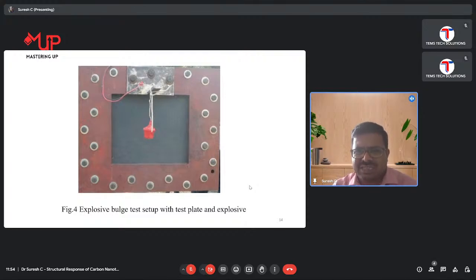The fixture is 550 cross 450 mm, and the center area exposed to the explosive will be 300 into 250 mm. So this is the fixture we have tested all our explosives. We kept the test plate in the fixture, and the red color which is hanging is an explosive. The distance between the structure and the explosive, we have maintained as 150 mm.